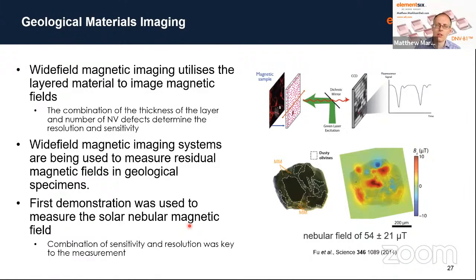Typically in geoscience, they've used things like scanning SQUID magnetometers, for example, but they just don't have the resolution. How they were able to do this is they found a meteorite, and just because of the geology of the meteorite, they were able to ascertain that it had not undergone any annealing as it went through the Earth's atmosphere. They were then able to measure the residual magnetization in that meteorite, and with the high spatial resolution mapping you can get with diamond, map out the magnetic field and therefore extract what the nebula field was at the time of the solar system's formation. There are lots of other applications where geologists are really interested in this. This wide field imaging technique is also used in other applications, such as biological applications and measuring magnetic fields from semiconductor chips.